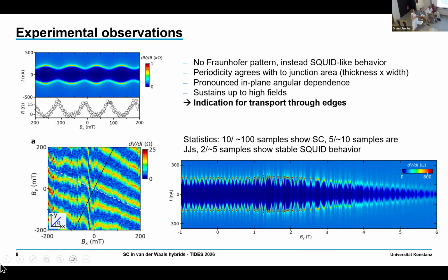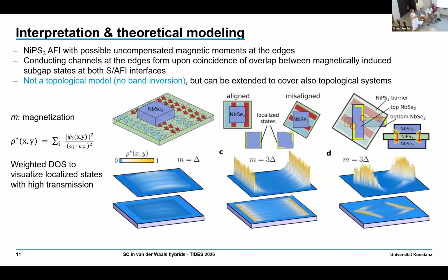What is special about these NiPS3? Why did you choose this material? Because it's an antiferromagnetic insulator. We wanted to probe an antiferromagnet instead of a ferromagnet to have, in principle, no net magnetization that could kill us. And we wanted to have an insulator, and then you go through the palette of van der Waals materials, and then you find this. There are probably 2 or 3 others, but this is the one that works. We tried different materials, and we also tried materials that were grown in home labs. And at the end, what worked is the NiPS3 that we could buy from HQ Graphene.